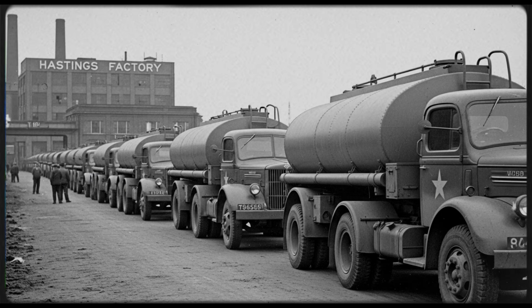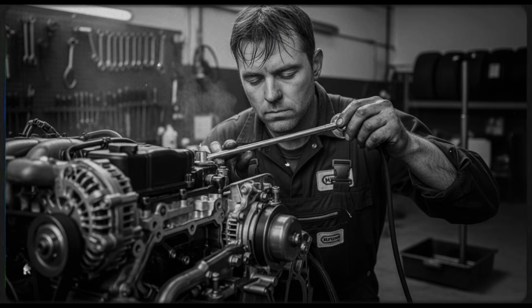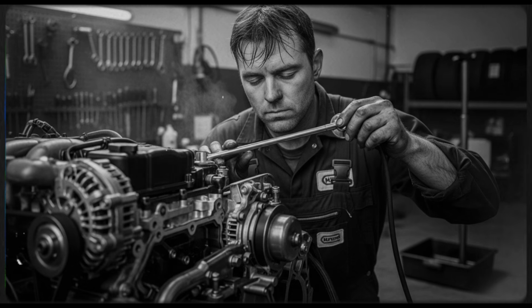Hastings established a merciless testing regimen. A sample from every single batch was subjected to a torture test. They installed the rings in a dedicated engine and ran it at maximum power and temperature for 24 hours straight. If a single ring showed any premature wear, the entire batch, thousands of rings worth tens of thousands of dollars, was immediately scrapped. There was simply no margin for error. A faulty ring wasn't a warranty issue, it was a potential death warrant.